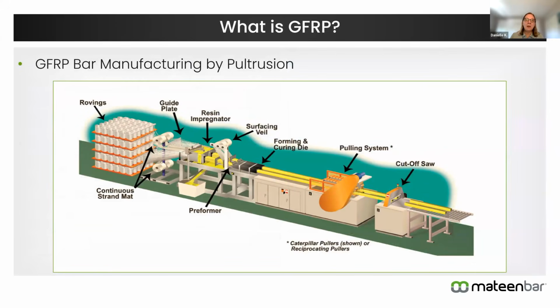So what is GFRP? Glass Fiber Reinforced Polymer. It's manufactured by a pultrusion process that is outlined in the schematic here at the bottom. If we look at the left-hand side of the figure, we see the spindles of glass roving. So think of the glass fibers. They're pulled through a guide plate and then pulled through a resin bath. So they're completely impregnated with the resin. They'll come along further down the production line here, the pultrusion line, and go through a preformer and then a forming die. This forming die also cures it, it heats it, and in this particular case, obviously, it's forming it into a round diameter bar that is in the shape of the rebar. Obviously, it's coming down the line and getting cut off at whatever length is required.